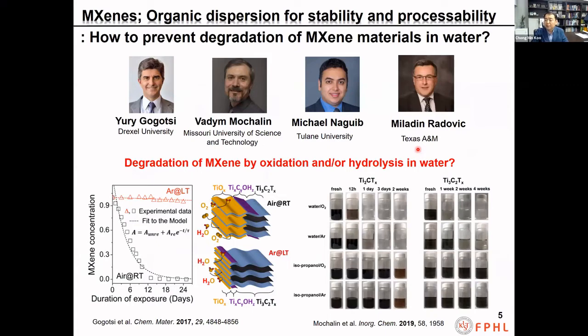My group is researching the synthesis of MXene, especially the synthesis of organic dispersions of MXene, for improving oxidation stability and solution processability. We are also researching several applications of MXene. As many speakers, including Professor Vadim, Michael Naguib, and Miladin Radovic, mentioned in their talks, MXene seriously suffers from degradation, especially in water. Professor Yuri's group first reported that MXene is very vulnerable to oxidation in water because of water and oxygen. The day before yesterday, Professor Vadim suggested that the degradation of MXene is caused not only by oxidation but also by a hydrolysis reaction in water.